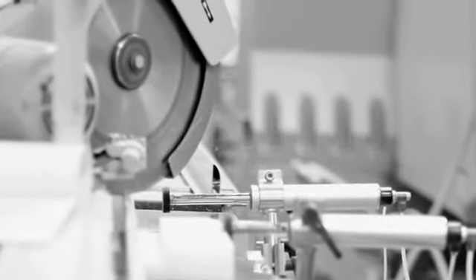Cutting resin with a saw is very easy to do to get those straight, nice finished cuts. Although they do have some unique considerations when you're actually doing the saw cutting. The first consideration would be that of the saw speed. If you feed it too fast, just like wood, you may see splintering. If you feed it too slow, you may actually introduce a little bit of melting of the thermoplastic materials.